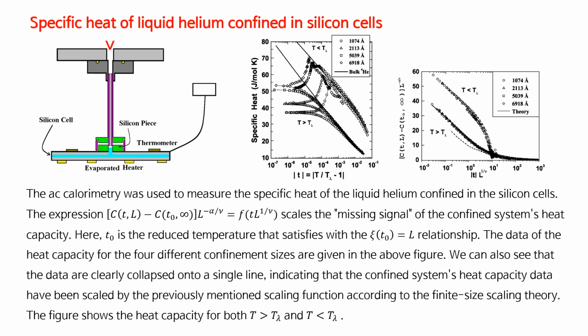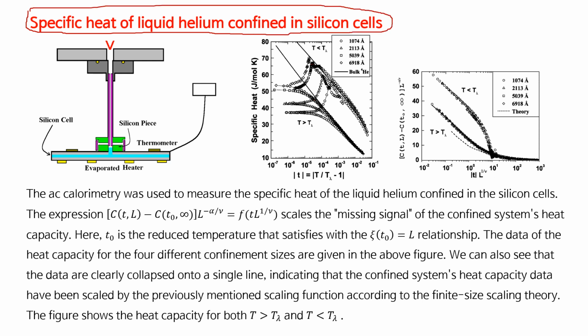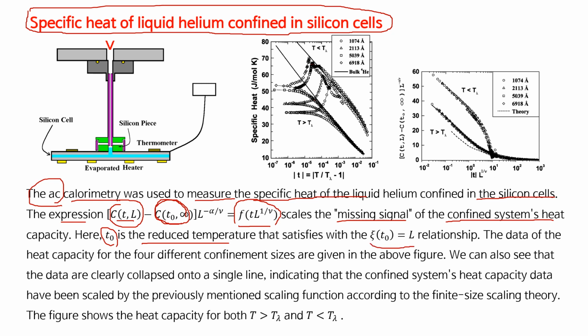Now let's see the specific heat of liquid helium confined in silicon cells. AC calorimetry was used to measure the specific heat of liquid helium confined in silicon cells. In the expression, there is the finite size system's heat capacity and there is the bulk system, so the specific heat difference is scaled by this function. So this expression scales the missing signal of the confined system's heat capacity. Here T0 is the reduced temperature that satisfies the xi t0 equal L relationship.